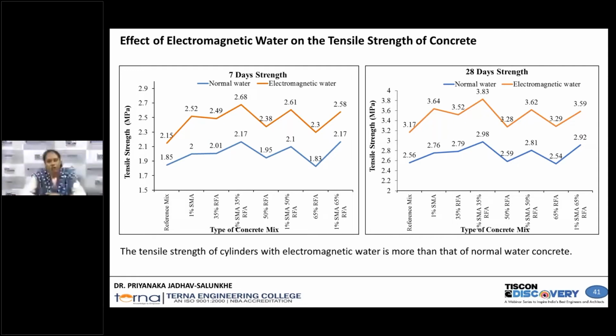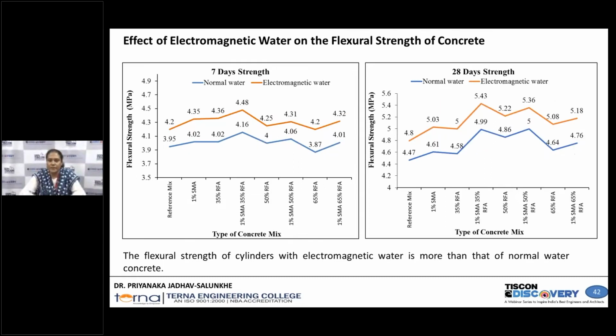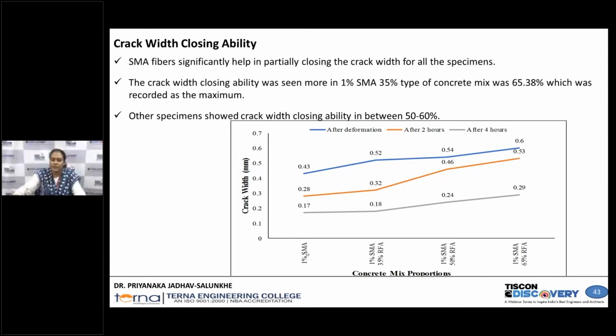Now, the main property of the shape memory alloy is the crack closing ability. Also, it is called the recentering ability of that particular structure. See in this figure, take again the example of 1% SMA with a reference concrete. After deformation, means immediately after testing, we observed the crack width is 0.43 mm, but after 2 hours it got reduced up to 0.28 mm, and after 4 hours it got reduced to 0.17 mm. Now this shape memory alloy can close the crack by 50 to 60%, and this is the main advantage to give an alarming failure of the particular structures.